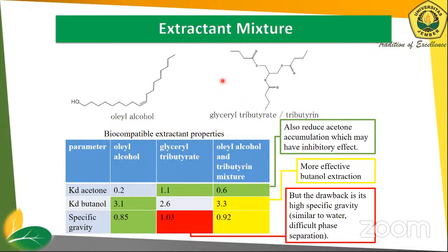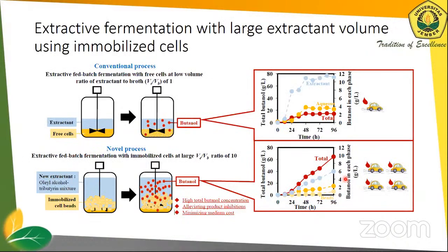Here for the extractant, we have to choose a biocompatible one, which is not killing the bacteria. We have the distribution coefficient for acetone and butanol here. We combine both of them. Oleyl alcohol here extracted butanol with about 3.1 distribution coefficient. And tributyrin is not frequently used, but we try to use it to extract the acetone as well. And this is the result.